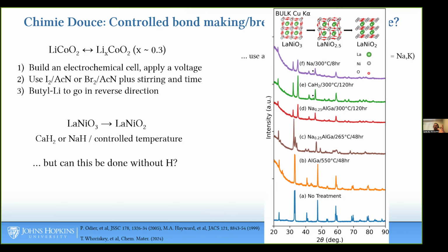And the cool thing here is when you change the concentration of the alkali metal in the gallium aluminum eutectic, you change the electrochemical potential. So rather than just sitting at a fixed electrochemical potential like with CaH2, by changing the concentration of the alkali in this, we can change the electrochemical potential. And what that means is that we no longer have to be quite as perfect in our temperature and timing, because we can continuously vary that electrochemical potential to a place where the reaction occurs, but we're not going to get over-oxidation. And so we're able to very controllably take LaNiO3 to the so-called brownmillerite, LaNiO2.5, and then also systematically to LaNiO2. And so this is just an example of a new chemical development inspired by a physics question that illustrates the frontier in complexity in materials synthesis.